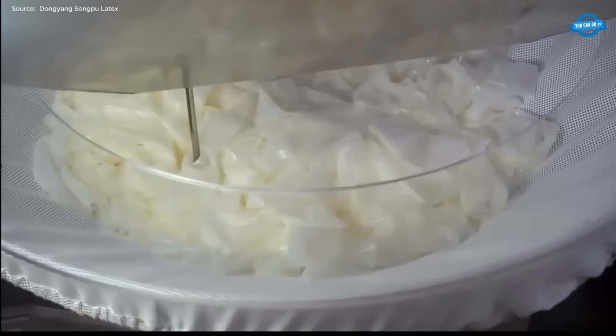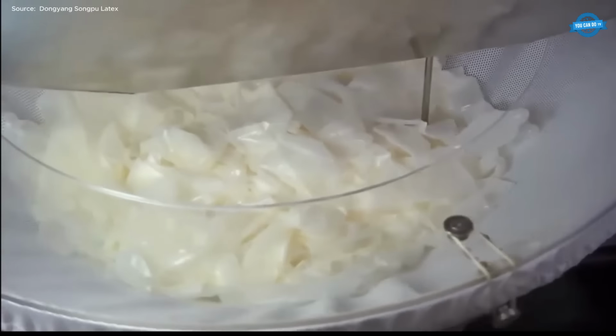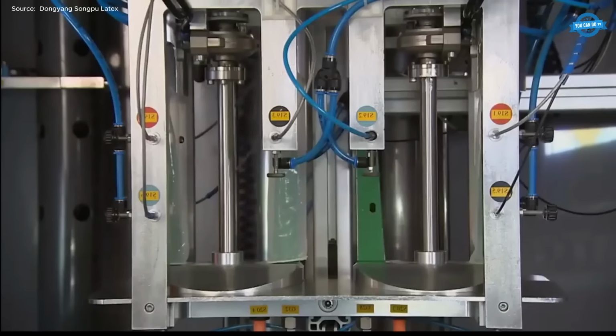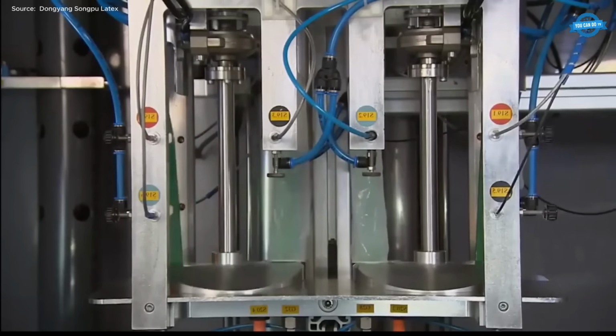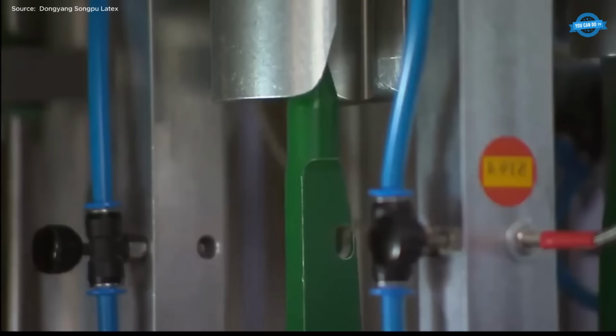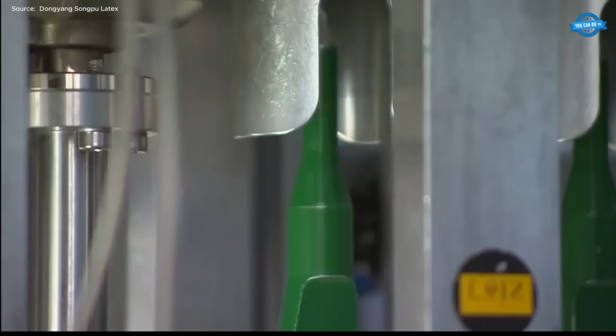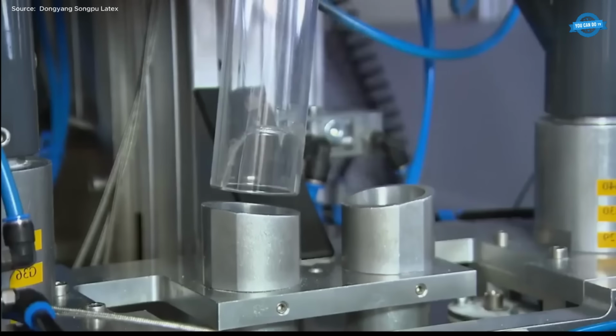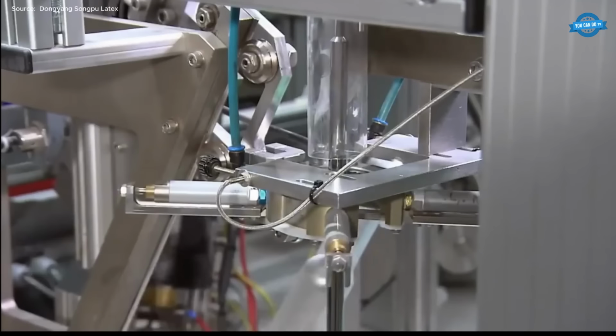Next, roll edging is done using steam and rubber rollers. The dipped molds are then dried at 90 to 120 degrees Celsius, followed by ammonia immersion, 45 to 65 degrees Celsius, 0.2 to 0.4% ammonia content.